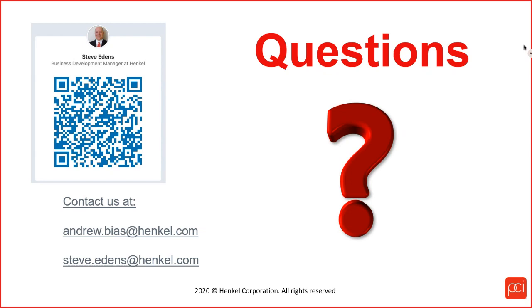What is the pH of the autodeposition bath, and is there a flash off time needed before you get to the dehydration? I don't know the pH off the top of my head. I would have to look it up on the MSDS or actually see an actual bath and put a pH probe in it. So I don't know the pH of the actual bath, but it is on the acidic side. It is lower. As far as flash off, it can go right into an oven. It doesn't need to flash off. Certain applications do need a dewatering zone, so that would be considered your flash. You'd have a lower temperature just to dewater the film, and then it would go into a cure oven past that. Okay. As far as the pH of the actual bath, approximately 3. Similar to a zinc phosphate tank. Okay, great, super.